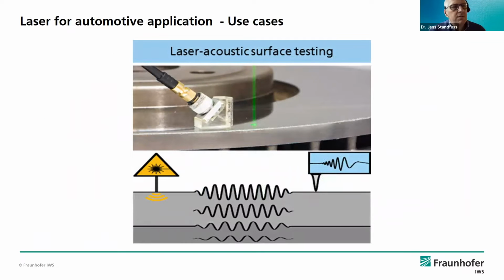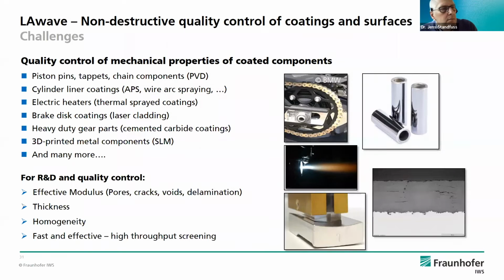If you have coatings, there are requests to characterize the quality of the coating and also the quality of the interface. One method is the so-called laser acoustic surface testing. A step backwards: what is the challenge in generally measuring or determining the mechanical properties of coated components with non-destructive technologies? This is necessary in a wide range: for pistons, for cylinder liners, for electrical heaters like these thermal spray coatings shown before, brake disc coating by laser cladding, but also for many other parts.